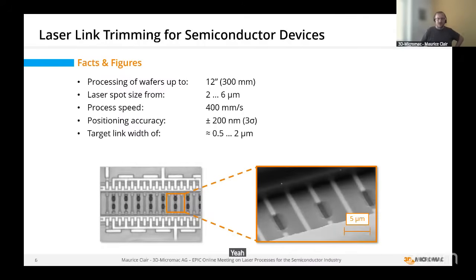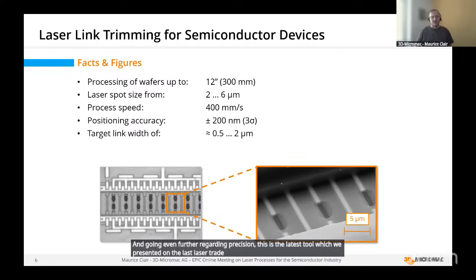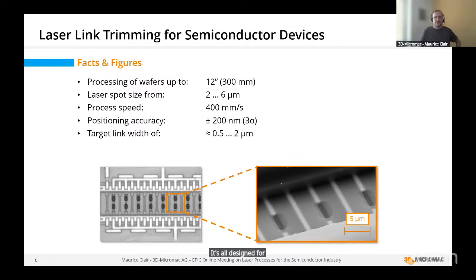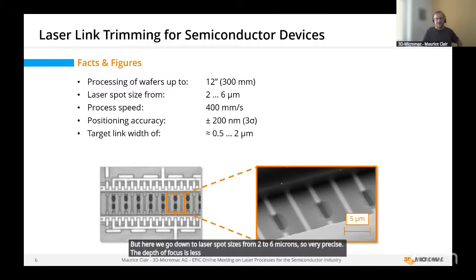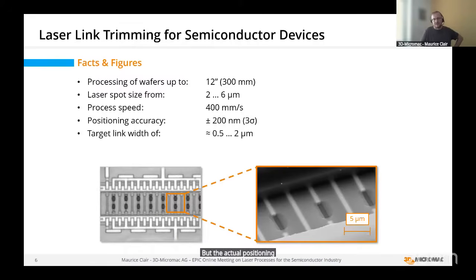And going even further regarding precision, this is the latest tool which we presented on the last laser trade fair. It's also designed for 300mm wafers. But here we go down to laser spot sizes from 2 to 6 microns, so very precise. The depth of focus is less than 1 micron for the process that we are running. And we are processing the wafers with a very high speed of 400 millimeters per second and very high accelerations. But the actual positioning accuracy that we need for the actual process of the link trimming is plus minus 200 nanometers 3 sigma. So standard deviation in X and Y combined is 60 nanometers in the system.